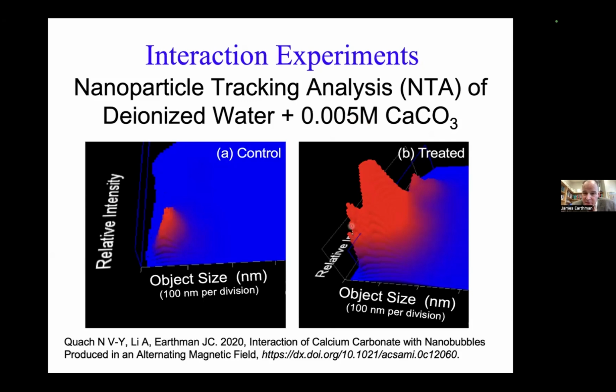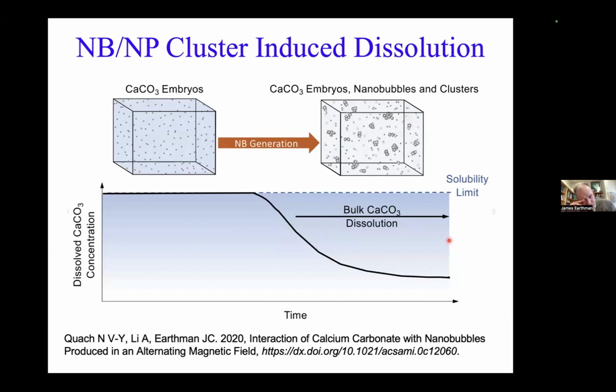When we put the nanobubbles in, same water, we get three peaks. We get a high peak, which is apparently the nanoparticles, because they have a higher index of refraction. They should scatter light more. The nanobubbles are probably this low peak here. And then we have this big peak in the middle that goes out to larger sizes. We believe those are the clusters, clusters of nanobubbles and nanoparticles together. And they go out to much larger sizes. It's hard to see on this image, but they do. So here's the theory for the interaction of nanobubbles and nanoparticles.